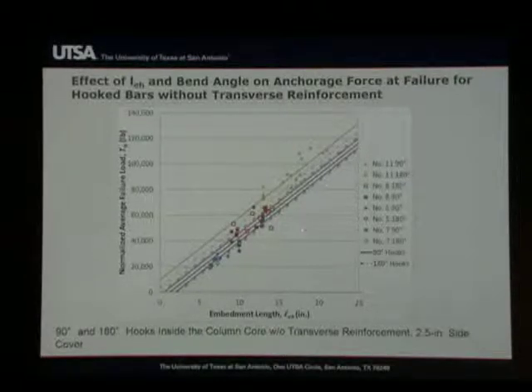And of course, we see in this case the analysis showing that the number 11 bars, for example, the green solid lines, will develop much higher bar forces than you would expect out of a number 5 bar, which is the blue in the bottom.